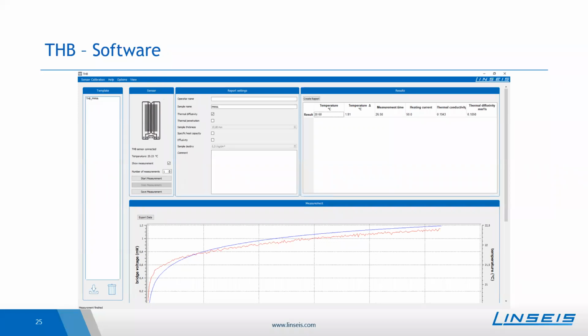The thermal diffusivity can be determined with the THB sensors and also with the QSS sensors. If one has knowledge about the density, one can also determine then the specific heat capacity, because the thermal conductivity is the product of thermal diffusivity, density, and the specific heat capacity, and then you can calculate that. The highest accuracy we achieve with the THB in determining the thermal conductivity. The accuracy of the thermal diffusivity determination is slightly lower, so let's say about 5 to 7%, depending also on the material. And this then leads to also a similar uncertainty in the specific heat capacity.